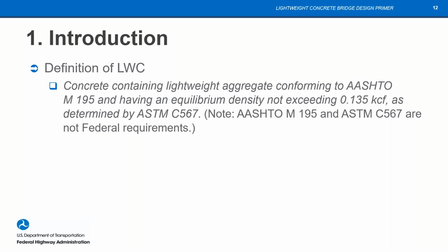The equilibrium density is defined in ASTM C567 roughly as the density of structural lightweight concrete after exposure to a relative humidity of 50% and a temperature of 23 degrees C for a period of time sufficient to reach constant mass. So it's essentially a dry density of the lightweight concrete.